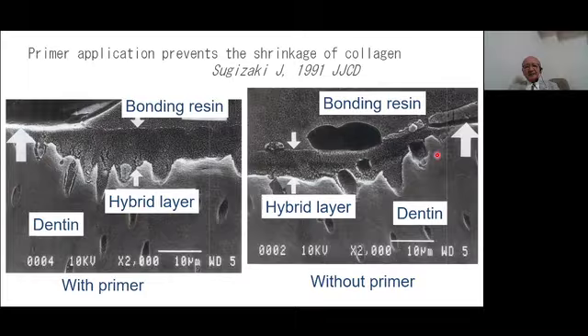By etching, the surface of dentin is demineralized. And the surface of the hybrid layer is depressed in the case when we did not apply the primer, even though the collagen should have existed at this height. This is because of the shrinkage of the collagen layer by the drying procedures. The shrunk collagen layer produced this hybrid layer-like structure. However, the top surface of this hybrid layer is lower than the original dentin surface.